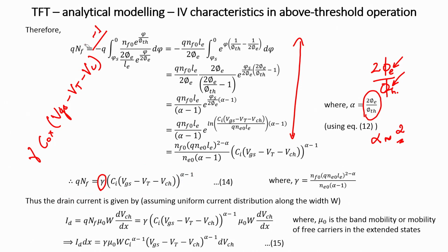So, therefore, crystalline silicon MOSFETs did not have any factor there, but this is the more general version of the semiconductor, and you find that alpha is twice Tc by T. So, that is your parameter alpha that depends upon the characteristic temperature of the gap states.